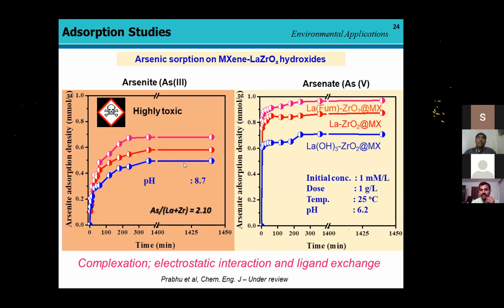Also, we have already developed a lanthanum fumaric MOF moiety. From the MOF, we developed lanthanum oxides, that means LOX. Then we combined it with a zirconia moiety and intercalated it on the MXene phase. Then we showed higher efficiency than the reported lanthanum-based materials until now. Also, the interesting phenomenon was that the lanthanum zirconia based material showed almost 80 milligram per gram of adsorption